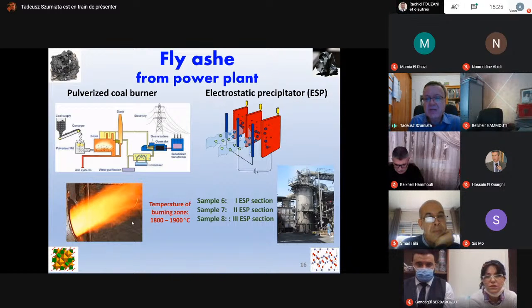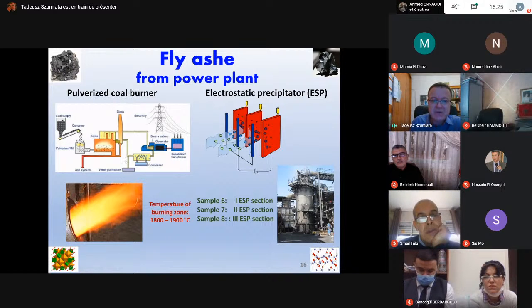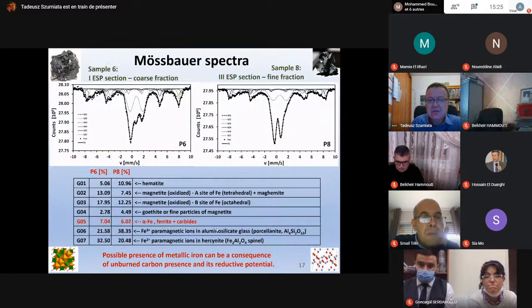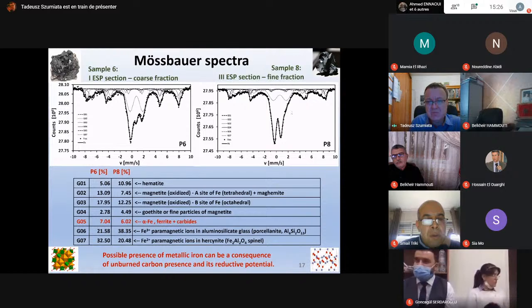And what about fly ash from power plants? In fact, this power plant is also located not far from my town. It is the biggest power plant using just hard coal. And here there is a very special pulverized coal burner with a high temperature burning zone, about 1800 Celsius. And fly ash is trapped by an electrostatic precipitator with several sections. And the spectra are quite similar, but this part of the paramagnetic part of these spectra connected with aluminosilicates is even more glassy, more white.